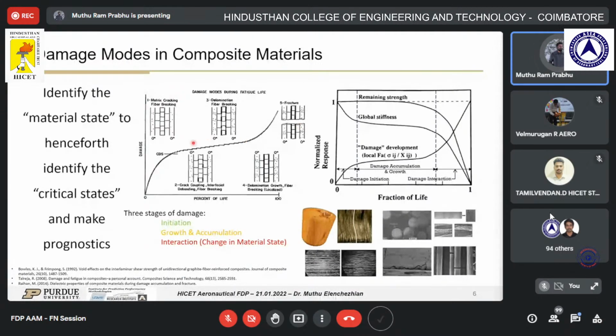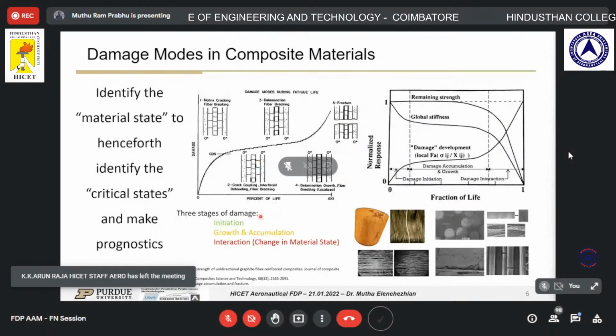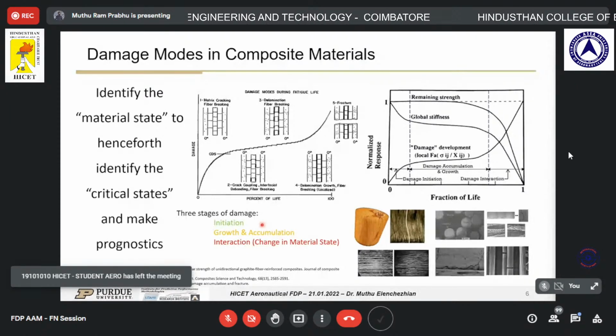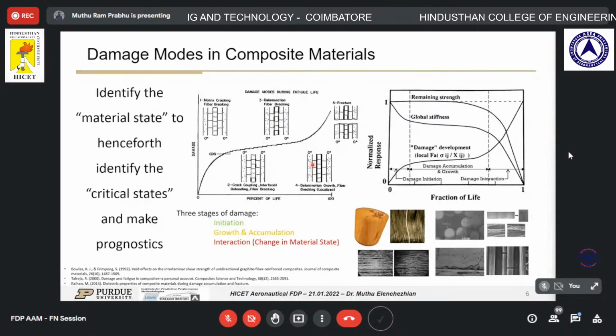And apart from only considering damage, we also consider stiffness, because the remaining strength as well as stiffness remain at high levels until it reaches the final stages. So based on these 2 plots, we can actually categorize damage into 3 stages: initiation, growth and accumulation, which is the second stage, and the final interaction stage where the fracture or the complete failure occurs. So while identifying damage and testing, we need to identify all the 3 stages, and the methodologies need to be developed completely to identify all the 3 stages.